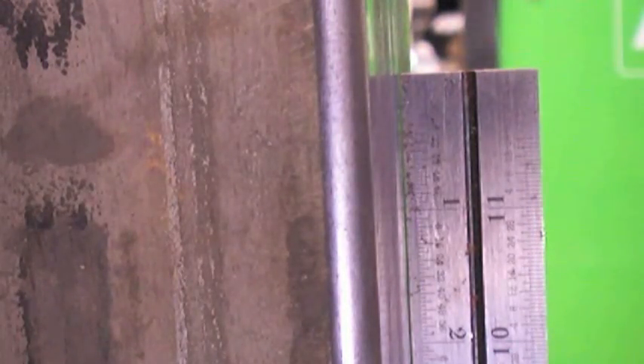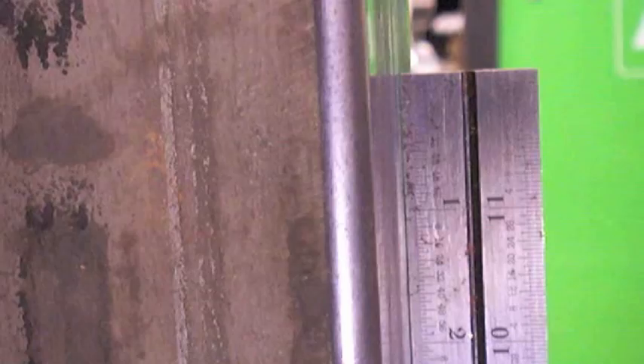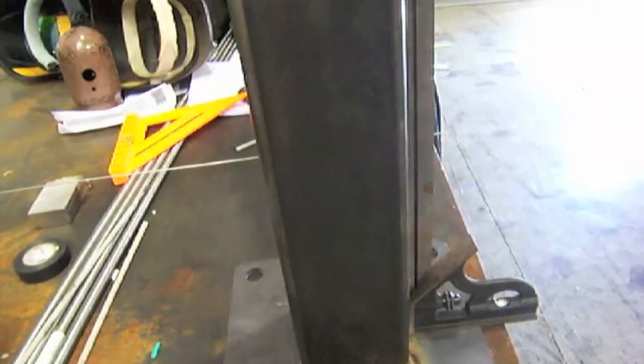Looking at the top of this square, I want to see about a 1/16th of light. You can eyeball this - everybody knows what a 1/16th is. I know it's at least going to pull that far. It all matters on how big a tack you put on and everything. But I'll keep the camera right here as I tack this thing. You saw I had a 1/16th gap. As that weld metal cools and solidifies, that gap is just going away and going away and then gone. That is deadnut square.